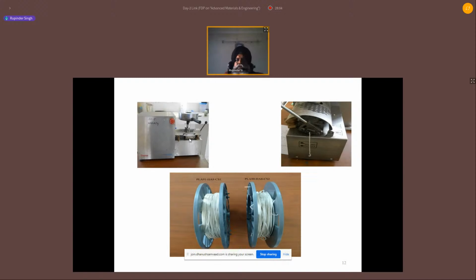You can see here some feedstock filament coming out through extrusion, and I am collecting this filament on this spool. In this particular picture, you can see 91% by weight PLA, 8% by weight hydroxyapatite, and 1% by weight chitosan that has been extruded. Now this will be fed as the filament that I have just shown you in the previous description of the FDM process, and I can print this to make some really useful part.